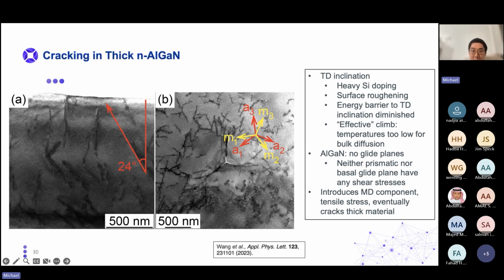This is a very well done threading TEM image of this crack that forms. And when the material cracks, what happens is you generate a lot of these threading dislocation defects. And even if you overgrow this and recover the morphology and grow to cover this crack up, these defects do not go away that easily. So what happens is at about 800 nanometers thick of n-type AlGaN, which I'll show later, the n-type AlGaN just all of a sudden gets a huge influx of defects, which basically completely destroys the efficiency of the material in terms of optical emission.